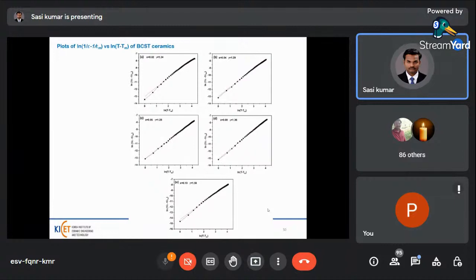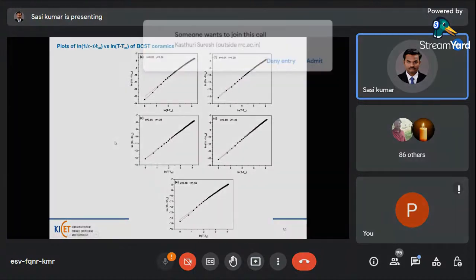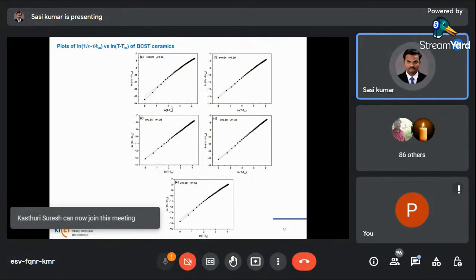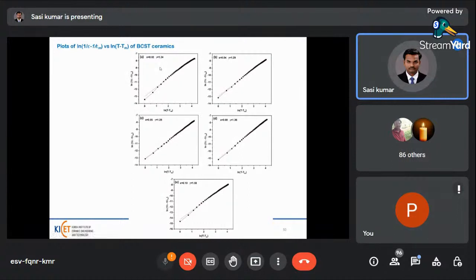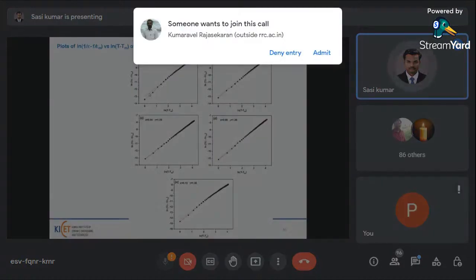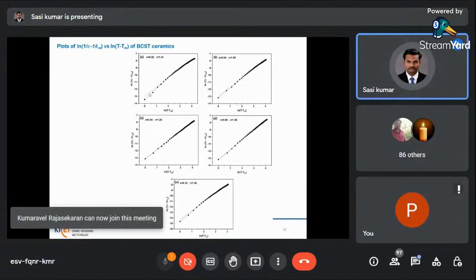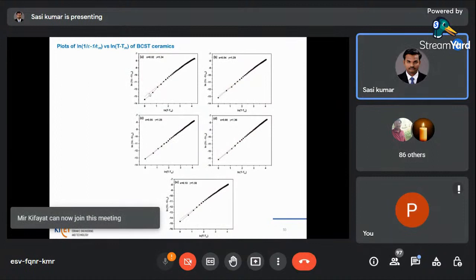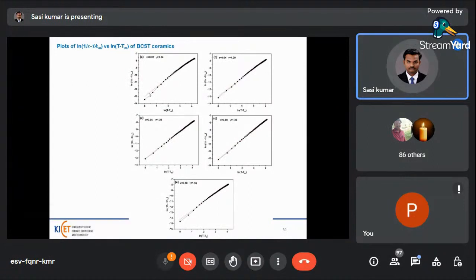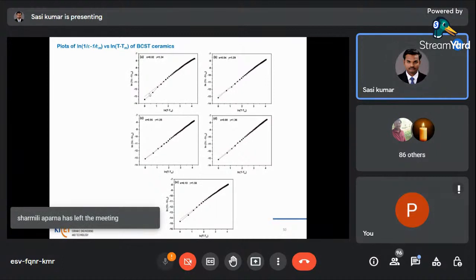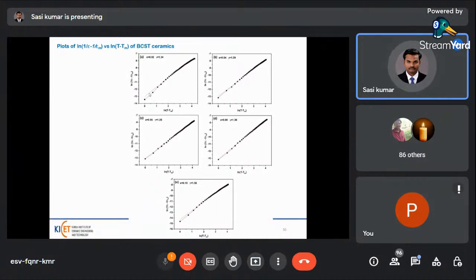Then the plots of ln of (1/epsilon minus 1/epsilon max) versus ln of (T minus Tm) of BCST ceramic. This plot gives the gamma value of the different compositions. This gamma value mainly indicates the relaxor properties of this composition. Whether this is a relaxor or non-relaxor material, we can easily find from the gamma values. If it is around 1 or below, it is a non-relaxor material. If the gamma value is equal to 2, it is a good relaxor material.